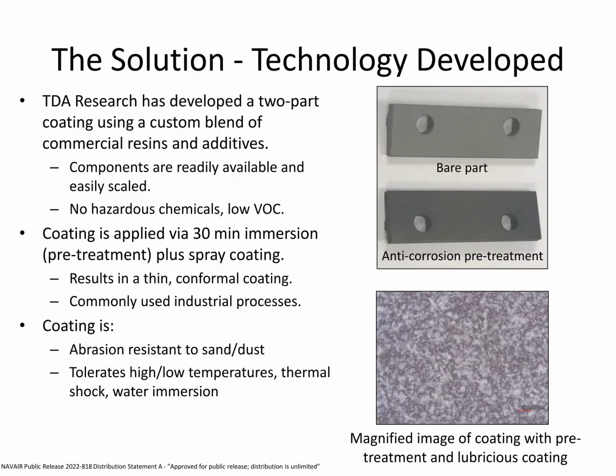It's very commonly used. Zinc nickel is used now by a lot of DoD as a replacement for cadmium, and this is a low hydrogen embrittlement plating, so it doesn't cause any stress cracking in the steel. The coating itself is a polymer. It's abrasion resistant to sand and dust. It's a very high temperature polymer, so at elevated temperatures when the gun is running, it won't melt or soften. And it's also hydrophobic, so in addition to the corrosion protection afforded from the lower sacrificial metal layer, the zinc nickel, the polymer composite on top is hydrophobic, and so it repels water.